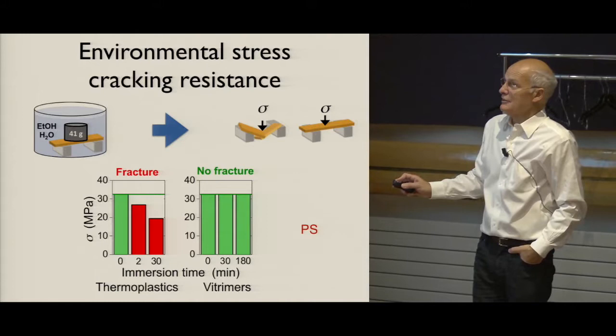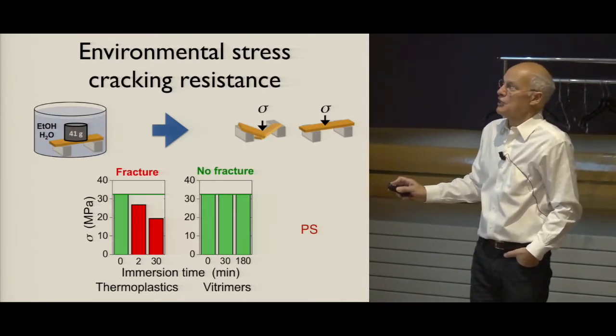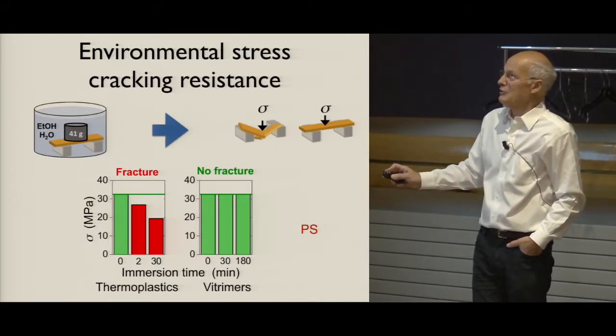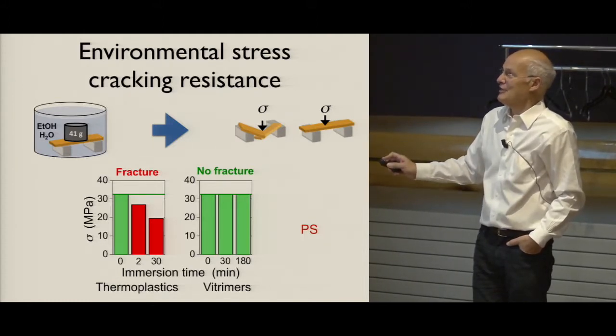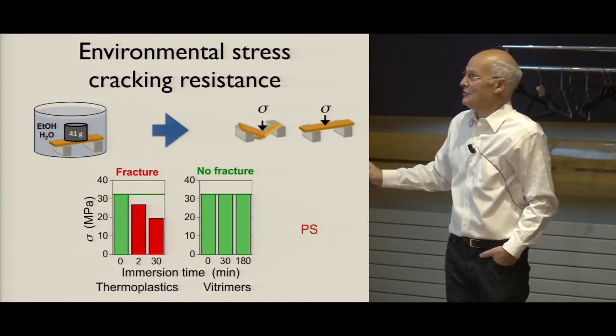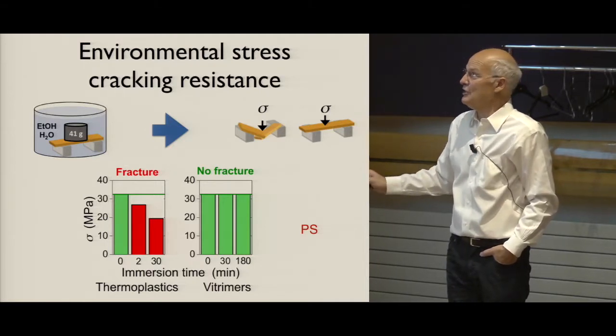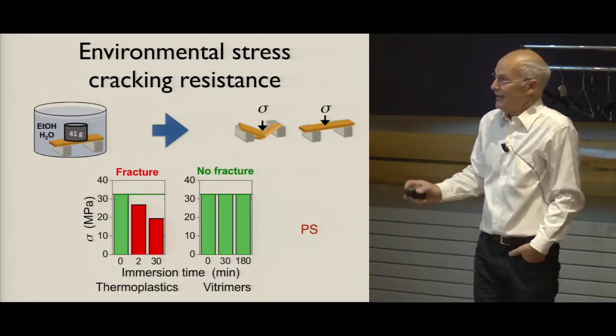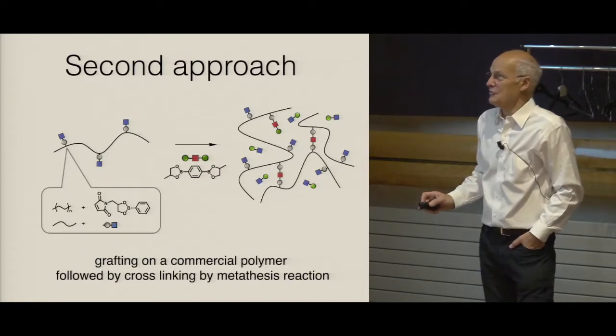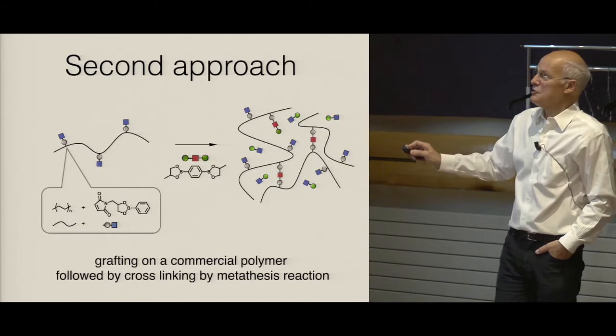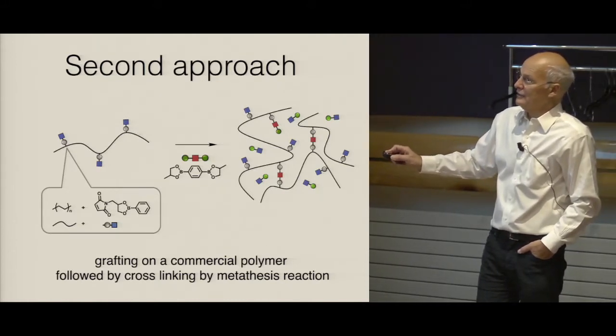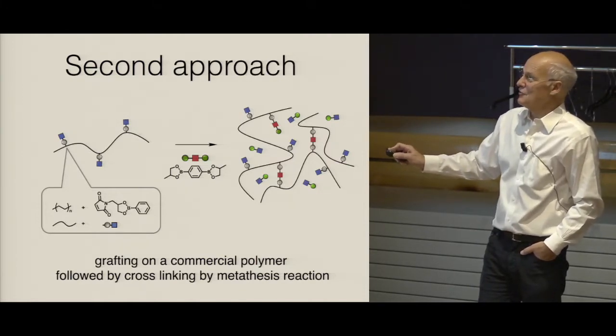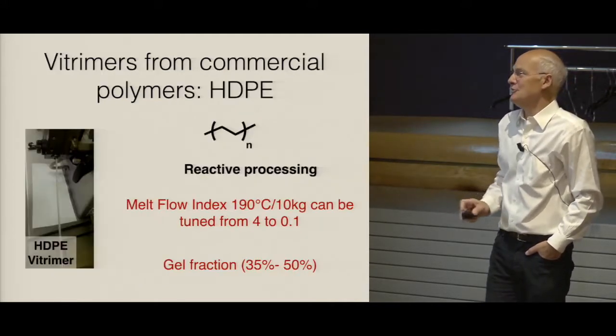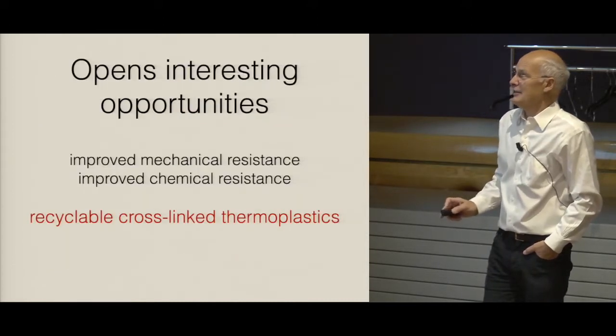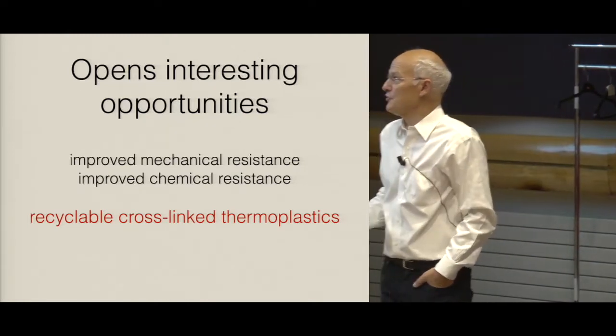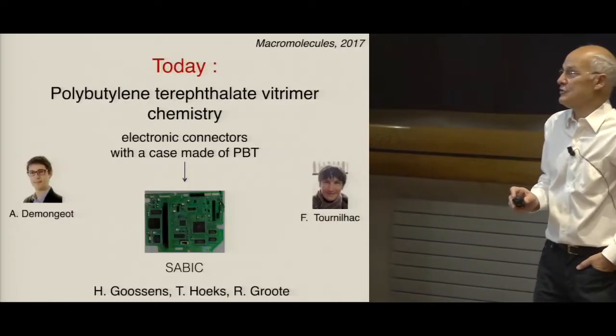So we can do the same thing with polystyrene. And if we do this stress cracking resistance experiment with which I started my talk, then the vitrimer resists the alcohol very well. So it will not fracture under the stress, and it can be processed, injection molded, compression molded, and it can be recycled many, many times, and it still has this exceptional solvent resistance. And we can do it differently also. We can buy a polymer, in this case polyethylene, and then we make a reactive ester. We graft the system in the melt, and again we use the metathesis to make a network and to relax the stresses. This modified polymer flows, and it has better mechanical resistance and improved chemical resistance, and it behaves like a cross-linked polymer, yet it is recyclable and reflowable.